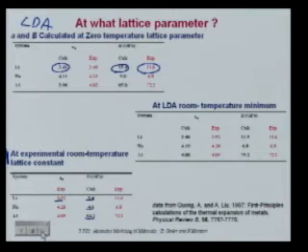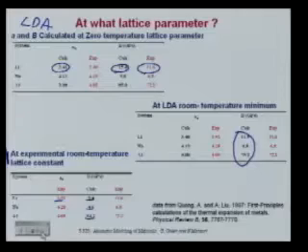So then you can do something else. You can do the sort of full-blown thing and actually try to find the equilibrium room temperature lattice parameter of your LDA, which isn't necessarily the real one. Remember, LDA will tend to over-contract things, and calculate the bulk modulus there. And that's what you get here. And of course, this is better. And it's sort of typical, because you're, in some sense, working in a consistent solution of the Hamiltonian. This is the minimum the Hamiltonian gives you, whereas at this lattice parameter, you're actually above the real minimum, and with this one, you're actually below it. So.